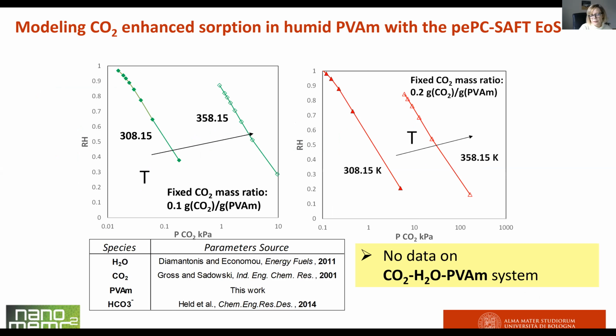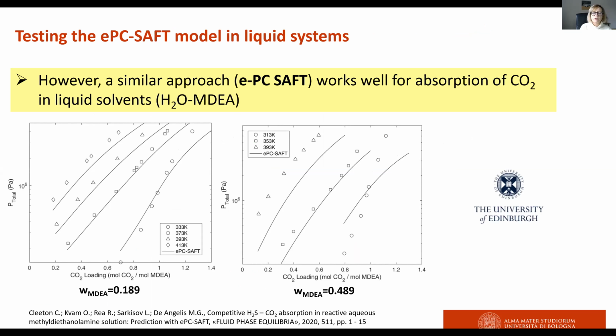Unfortunately, we do not have experimental data for the enhanced absorption of CO2 in a humid polyvinylamine, but you can correctly see the trends and understand what is the pressure of CO2 required to have a certain fixed CO2 uptake in the membrane at each value of the temperature and at each value of the relative humidity of the membrane. As I told you, we do not have experimental data on absorption, but we tested this same approach not on a polymer membrane, but on a liquid system, in particular on systems formed by water and MDEA, for which there are many experimental data. And the same model works well in predicting the data.